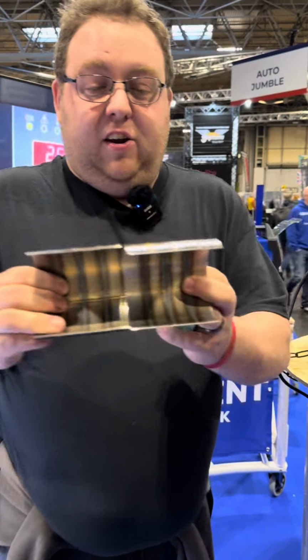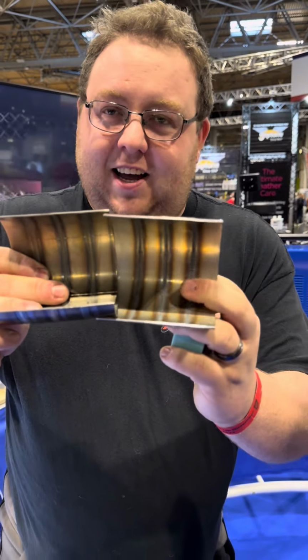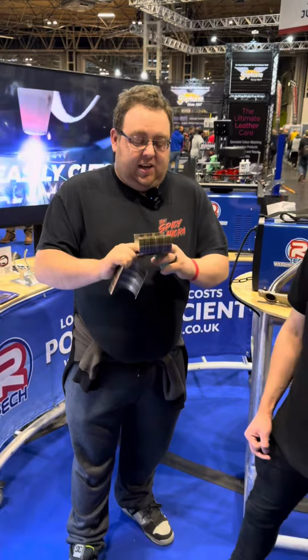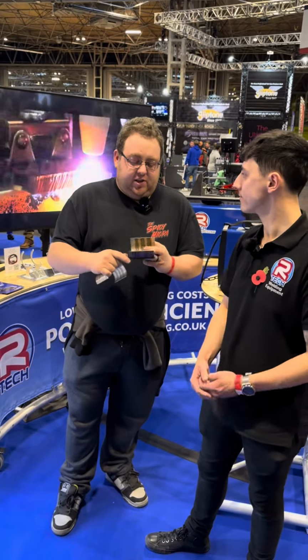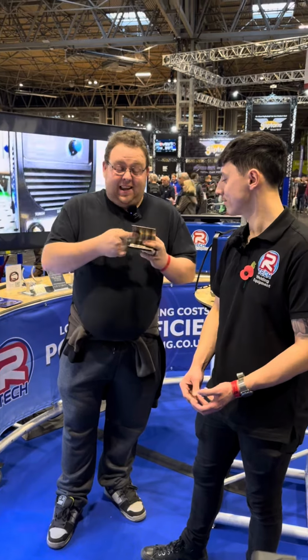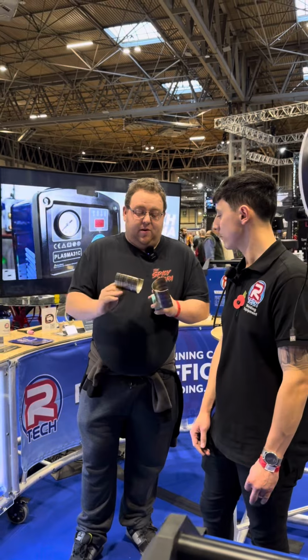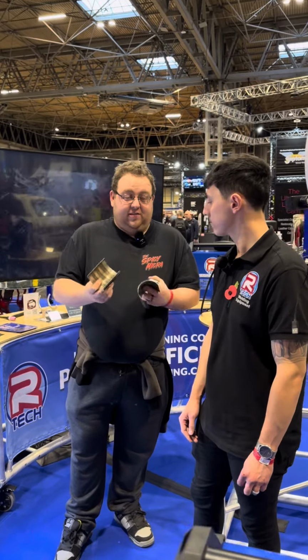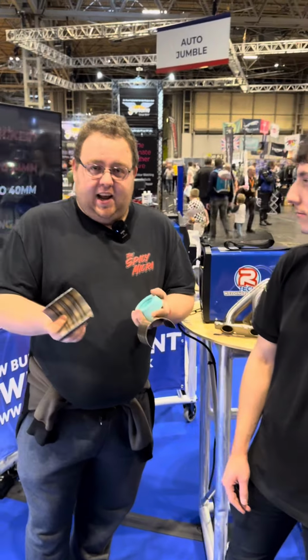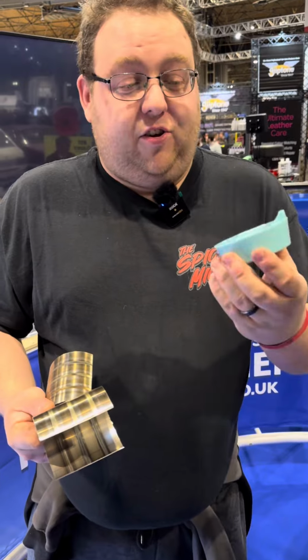Whereas obviously you can see on the purge side by side that this side's nice and flat and this side's rough. And ultimately, especially if you're on like a turbocharged application on like an exhaust manifold, these can actually break off and they will go through your turbo and ruin your turbo. So extremely important to purge well stainless steel, as well as other materials such as Inconel and titanium. And these are the absolute perfect product to do that with.